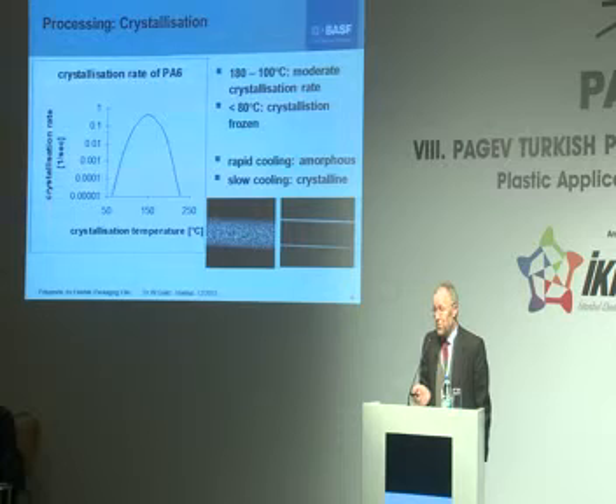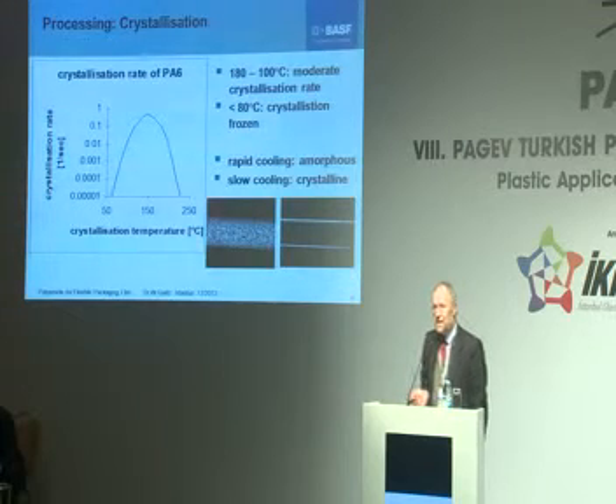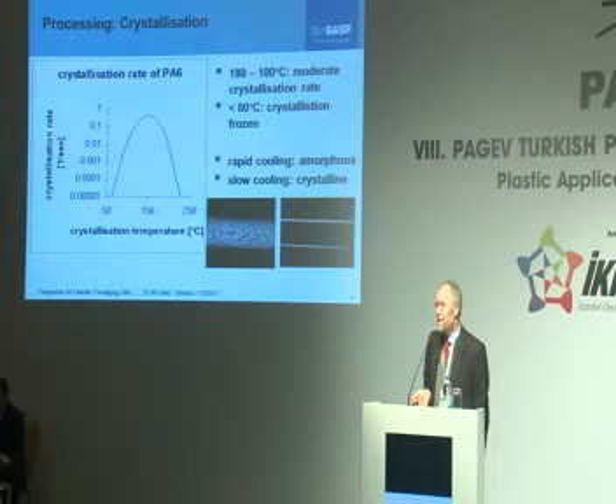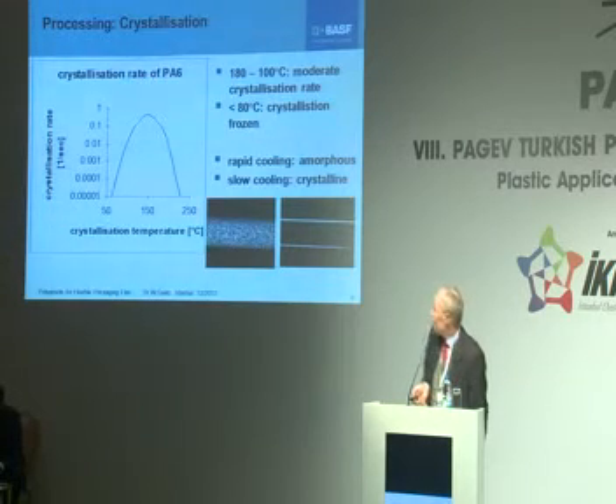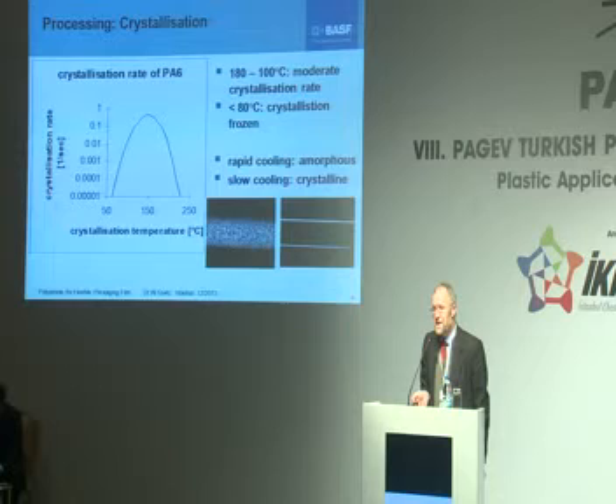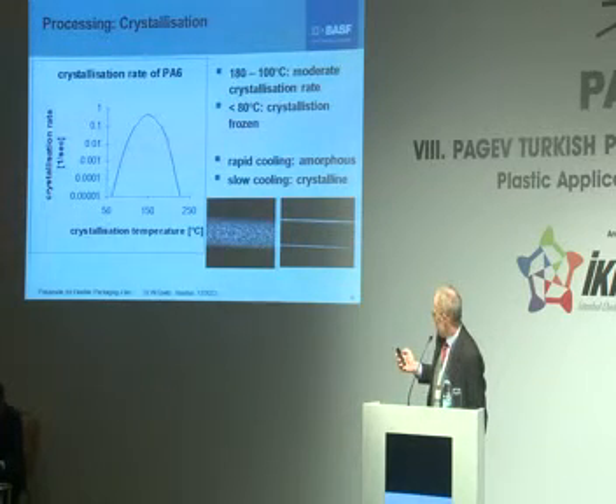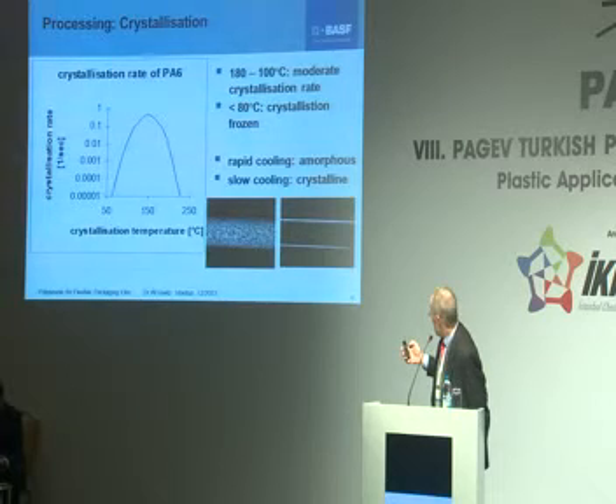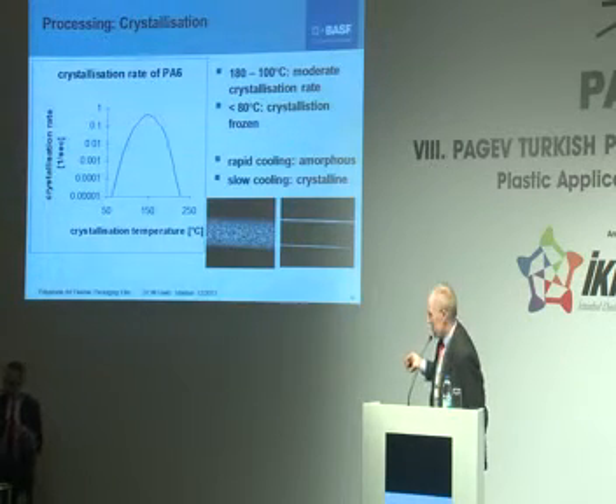When polyamide is extruded, it gets a lot of its property profile from its crystallization, and polyamide is a material of intermediate crystallization speed, unlike a material like high-density polyethylene, which would crystallize very fast. On the other side, PET crystallizes rather slowly. Polyamide is in the middle area, with a crystallization speed that allows tailoring the degree of crystallinity in a wide range by shock cooling, shown on the right side.